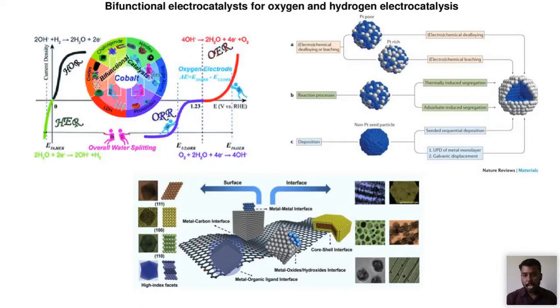Different strategies are available. You can refer to the literature, and you can choose the best method for preparing a material. Like electrochemical dealloying, you can apply a particular potential. For instance, if you have platinum palladium, you can leach out some palladium atoms by applying some oxidation potential, and this is called electrochemical dealloying or leaching. In that way, you can create some pores in your alloy.